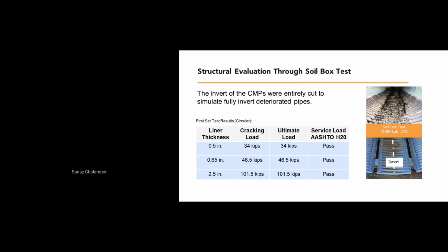So the results were very interesting. According to the AASHTO LRFD, the calculated pressure on top of a flexible pipe due to the H20 truck service load is 13.75 kips. All the numbers that we got for the cracking load and ultimate loads were higher than that 13.75 kips, even for the lowest thickness, which was only 1/2 inch. And this test showed that this system can be used as full structural in these applications.